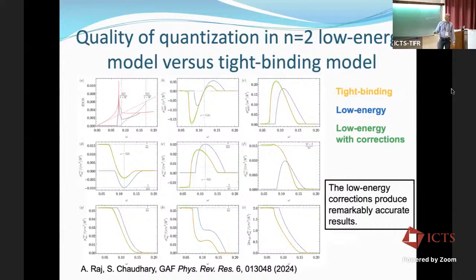And so one can check this numerically. Essentially, this is the sort of thing to look for. This is the sum of all of those. You see perfect quantization. And the important point that I want to emphasize in these figures is the comparison and contrast between three different approximations. So one is the low energy theory that I showed you around that Weyl nodal point. Another is a full tight binding model for which that theory is the low energy theory. And then the green is corrections, leading order corrections added on to the low energy theory that bring you a little bit closer to the tight binding model.